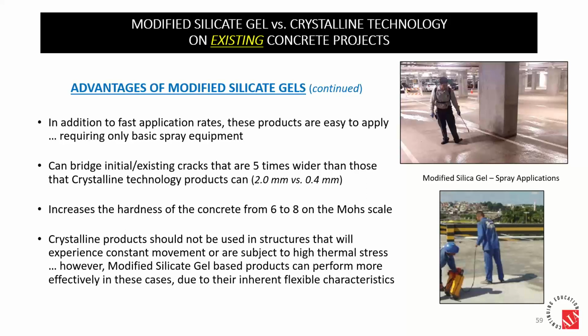Another advantage is that the silicate gel strategy will increase the hardness of the surface of the concrete from 6 to 8 on the Mohs scale. And if you're not familiar with that, 8 is the equivalent of granite. It's like taking 3,500 PSI concrete and making it the equivalent of 5,000 PSI. So that is an advantage to limit surface cracking and to limit wear. So a bridge or a parking structure, that concrete does actually wear a small layer off.